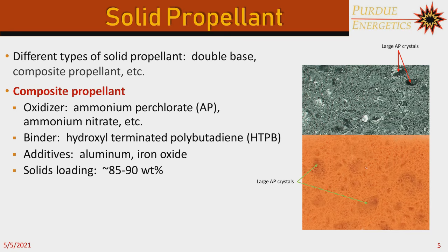So, the higher your solids loading of particles, the more difficult your propellant is going to be to process, because it's going to be more viscous. And the same thing applies if you use a lot of small particles. So, for example, if you use a lot of nano-aluminum, that's also going to increase the viscosity of your mixture.